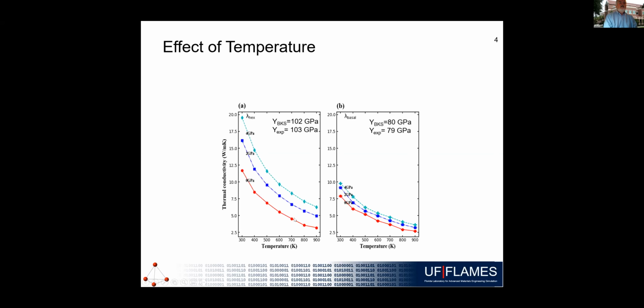We're seeing the temperature dependence here, which is decreasing with temperature as we'd expect, and an increase with pressure. This is a similar result in the basal direction. Thermal conductivity goes down with temperature, increases with pressure, and this is done with an atomistic potential. It turns out this atomistic potential gives very good agreement with experimental values for the Young's modulus, for example. So this seems to be a reasonably reliable potential for elasticity. Whether it's reliable for thermal transport properties is a less resolved question.